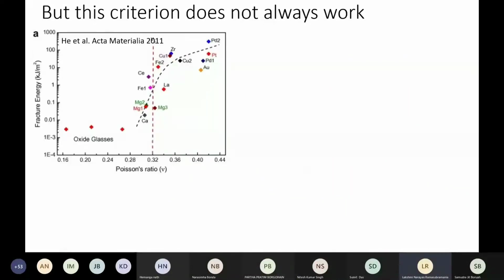But unfortunately, this criterion does not always work, because what we see is that when you have a collection of different metallic glasses, they observed a critical Poisson's ratio of 0.32, below which you are going to have brittle glasses, for example, iron-based glasses, magnesium-based glasses, and calcium-based glasses, which have very, very low fracture toughness. These have been marked with different kinds of symbols, and they have also been labeled. And when you go to higher Poisson's ratio, you expect all of them to have very high fracture toughness. For example, copper-based, iron-based, some zirconium-based also, they show very high fracture toughness.